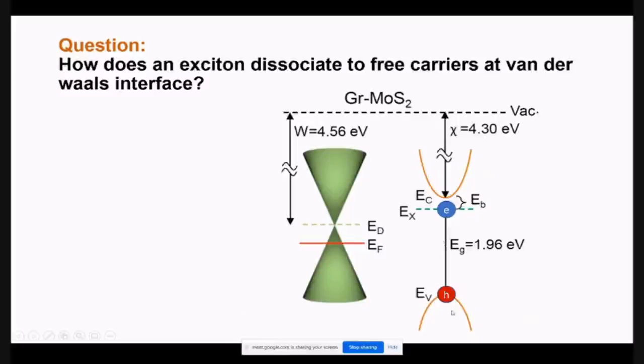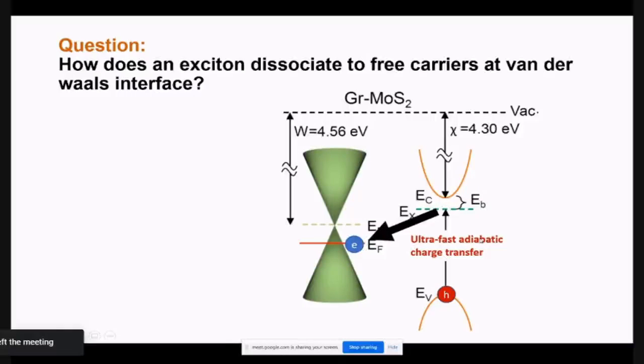The moment light comes in, the electron and holes are created. This is how the energy band diagram looks like. You can see the graphene has a work function of about 4.56 electron volt, and that of molybdenum disulfide, or most of the chalcogenides, is on the order of 4.3 electron volt of electron affinity, and that leads to this kind of alignment. Okay, and when light comes, the electron forms below the conduction band by a certain amount of energy called the binding energy. That's the excitonic level. It sees a lower energy state which is available to it, which is graphene, and immediately an ultra-fast adiabatic charge transfer takes place. How that charge transfer initiates is a question that is still a matter of debate. There are people who came up with an effective Hamiltonian which initiates the charge transfer from the MoS2 layer, or the chalcogen layer, to graphene. But it is an ultra-fast charge transfer.